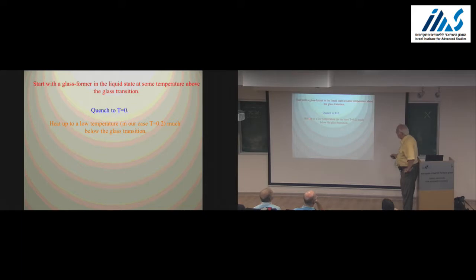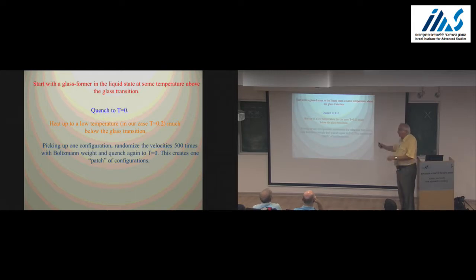Now, heat up to a low temperature. Let's say in Lennard-Jones, T equals 0.2, because the glass transition, so to speak, is around 0.5 or 0.46 or something, much below the glass transition. Now the system is running a little bit with molecular dynamics at some temperature, but every particle is within a cage. Pick up one configuration at this T equals 0.2, one configuration in space. And now randomize the velocities, let's say 500 times. Of course, you could do it 1,000 or 2,000 times, but we are lazy, we do it only 500 times, with the Boltzmann weight at this temperature 0.2, and quench again each one of those.